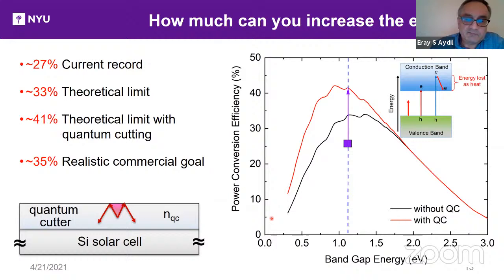Now, immediately you might be wondering, well, this quantum cutting device is going to emit isotropically. That is, it's going to emit in all directions, and some of the light might escape the material, and instead of going into silicon, go back out of the cell. And that's true, but there's something working towards you, and that is the quantum cutting materials, the ones that we're talking about, have high enough refractive indices that the loss cone here is actually small. And the light is trapped by total internal reflection inside that film.